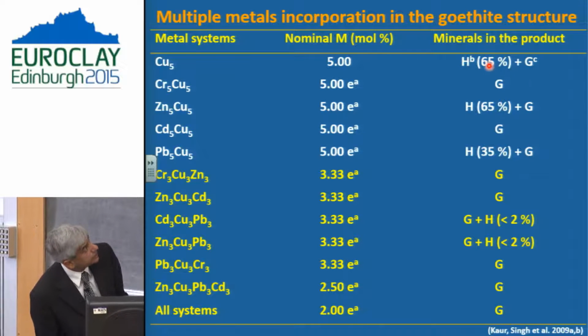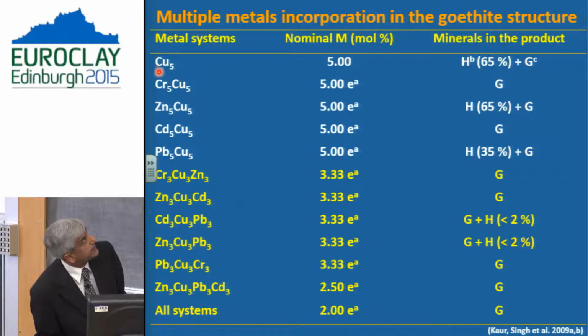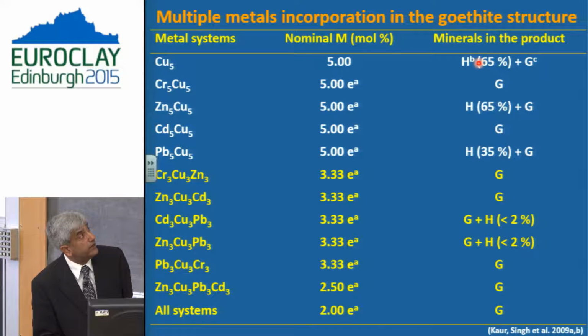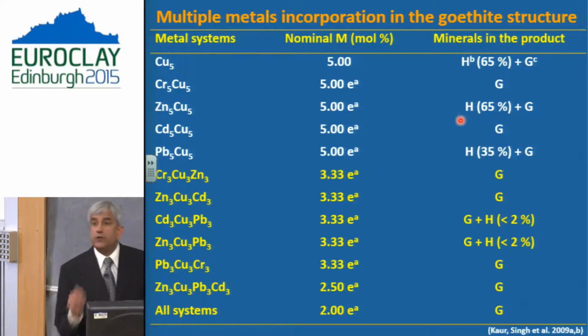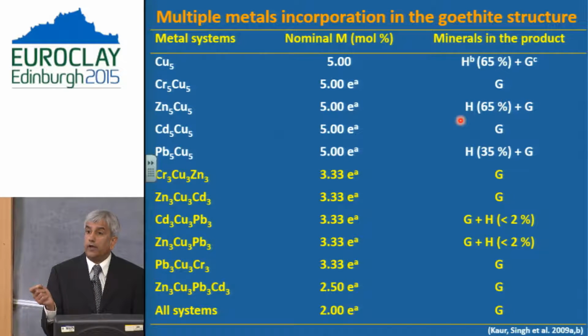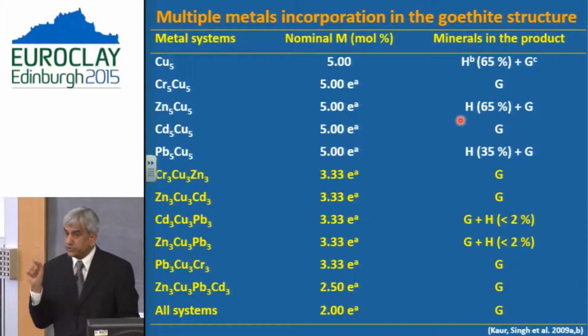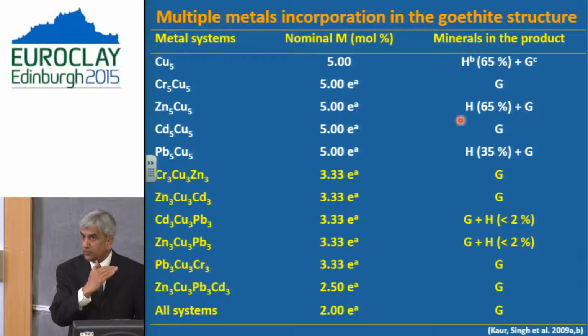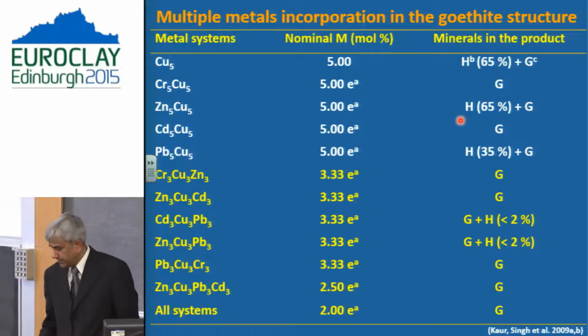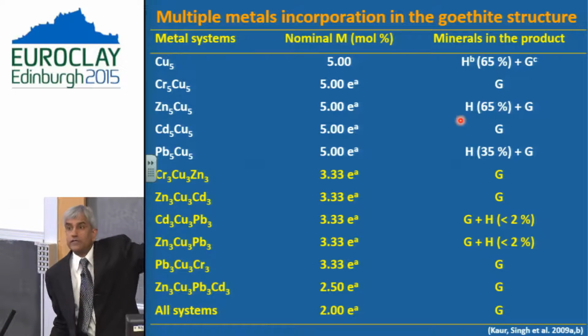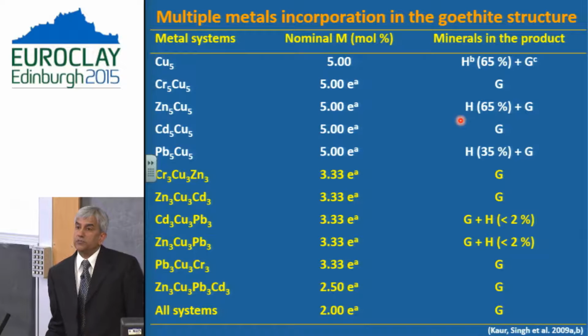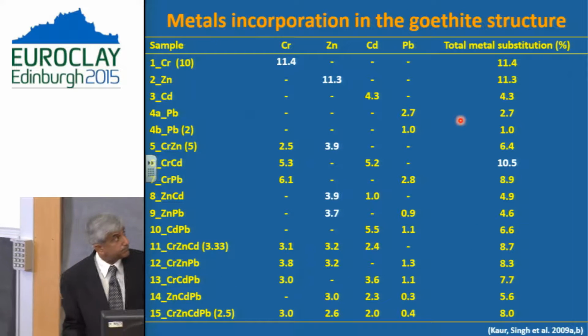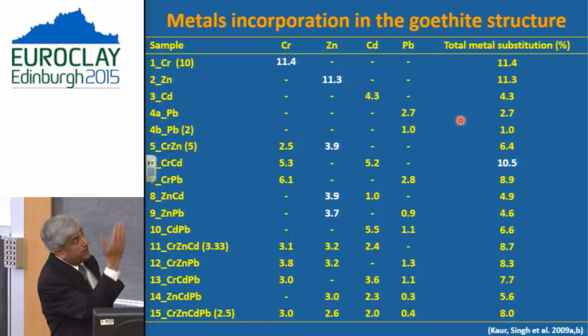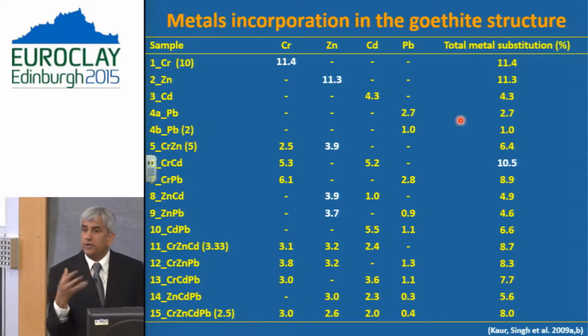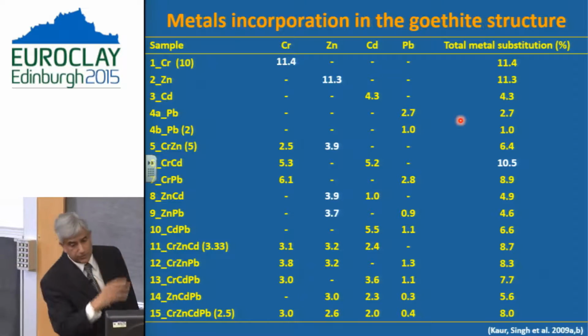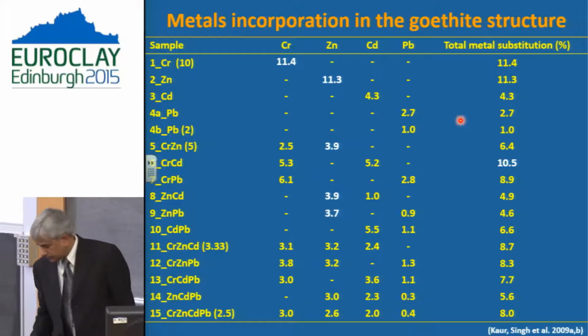One thing which I want to point out from this slide is that in case of copper, you get the formation of hematite preferred over goethite. Copper was not substituted too much in the goethite structure. We have seen that before, but when you look at the multiple system, in the copper case, you get preferred crystallization of hematite in the system. Different amounts of metals were incorporated in the mixed system, and I'll present a summary of those later on. I think there's too much information here.